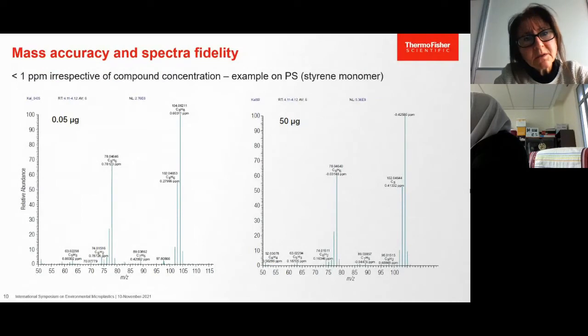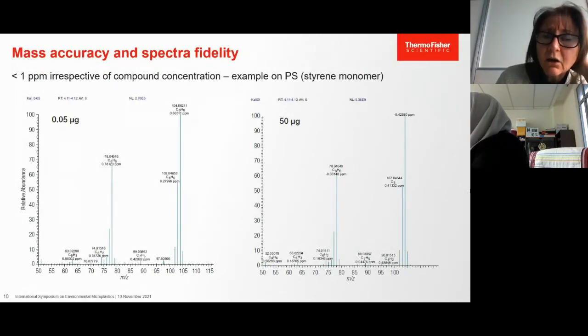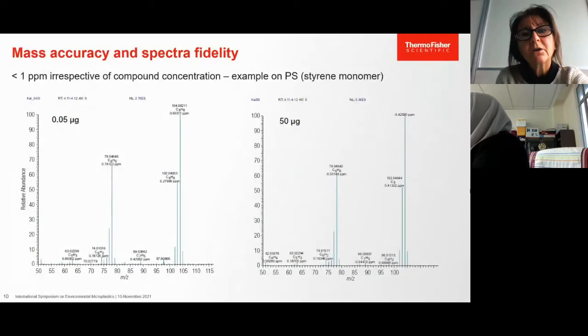In addition to the response linearity, mass accuracy of target compounds was verified across all concentrations. Accurate mass information is, in fact, critical to avoid misidentification and erroneous quantification. For all the target compounds, the mass accuracy was less than 1 ppm, irrespective of the matrix complexity or the concentration level. So here is an example of consistent high mass accuracy for all the ions of the mass spectrum for styrene at the lowest and the highest concentration level.